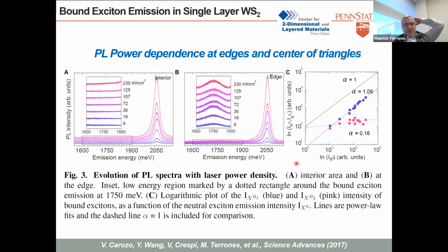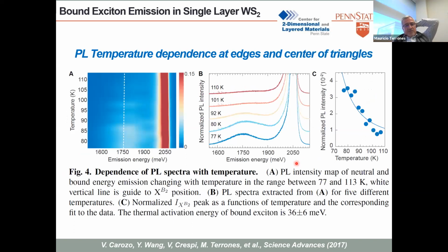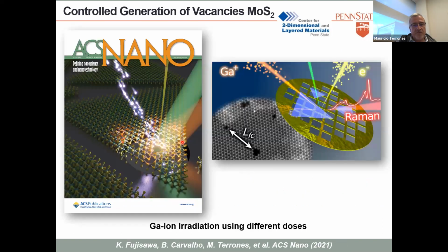So this is nice work, and you can see here, at low temperature, you can see the bound exciton very clearly. At room temperature it is not there, or close. It starts to appear at 90 K. So this is a nice result, I think. One thing that we are now trying to understand as well is these vacancies. We know that the sulfur vacancies create this bound exciton.